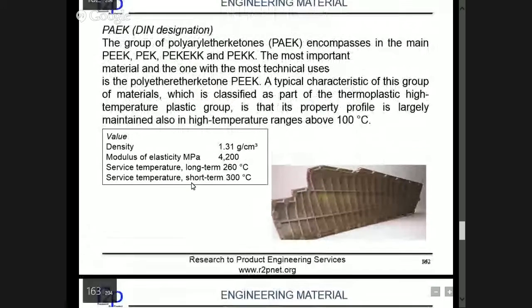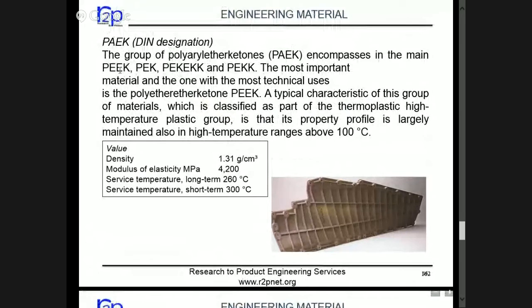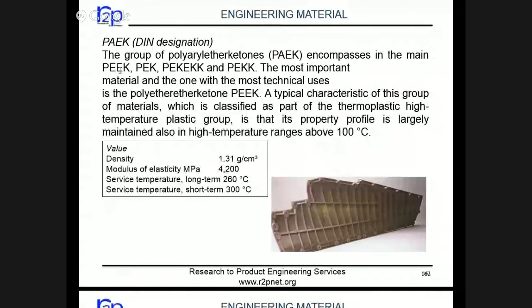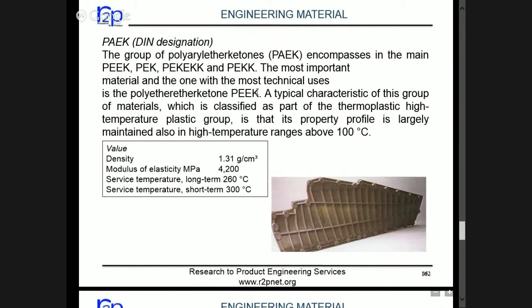Some, only the last two slides I will show you. One is the PEEK material. PEEK is a very high tensile strength material which is replacing many areas of steel also, like in gears or highly loaded covers. So this is replacing some of the steel also. The best part is why this is able to replace: its service temperature goes up to 260 degrees centigrade. Normal plastic is 70-80 degrees. You can take it with some fillers to 100 degrees. But PEEK you can take up to more than 200 also. That's the best part of PEEK.